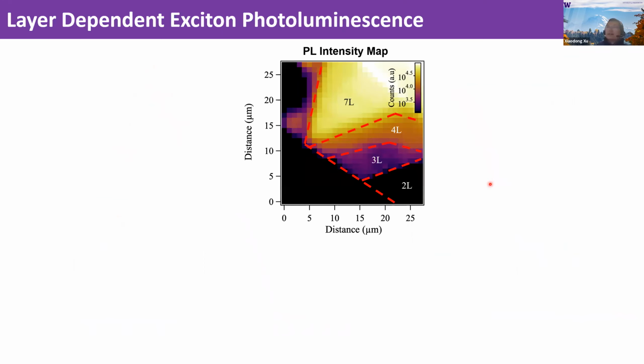Another interesting feature that usually arises in layered materials is layer dependence. So we also performed these exciton luminescence measurements as a function of layer thickness. The plot I show you here is the PL intensity map as a function of layer thickness. You can already see that the signal drops dramatically from 7-layer to 4-layer, 3-layer. In the 2-layer, we basically see nothing.